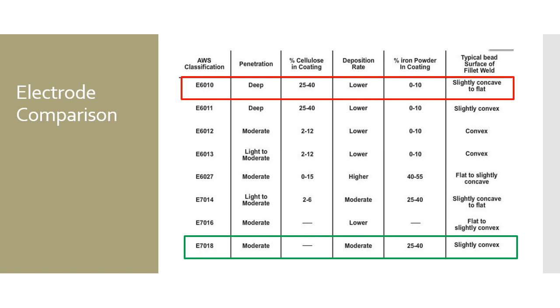You can see the percent cellulose in the coating. 6010 has up to 40% of that electrode coating as cellulose. It is covered in wood chips. 40% of that coating is wood chips, up to 40%. You go down to E7018, there's none. There's zero cellulose in that coating.